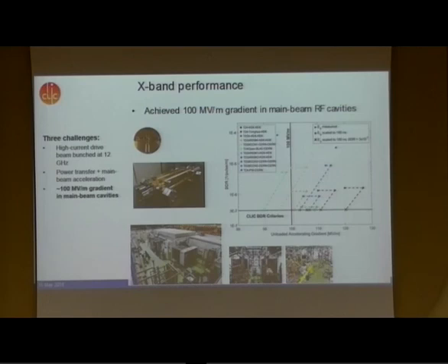In principle, if we could put higher electrical fields and more power into these structures, even though the RF distribution in itself is difficult, then we will have too many of these breakdowns. These breakdowns are not fundamental, but they do disturb the beam, and we have a criterion that we should not lose more than 1% of the luminosity in a 3 TeV machine due to this arcing, which has the potential of giving the beam a little kick. It doesn't have to do it, but it might do it. So we put a limitation from that type of criterion. Next slide.